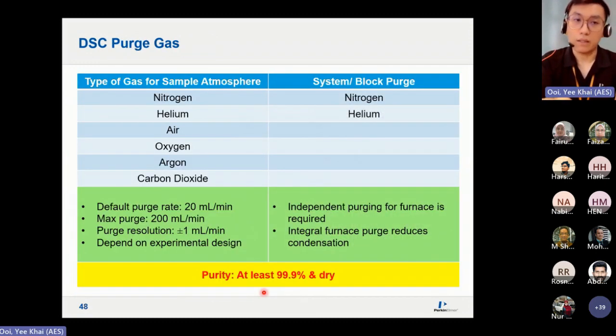Like TGA, DSC also needs a purge gas. Usually we use nitrogen. Why is it so? Although there's no decomposition, you still want your sample to be under an inert, controlled atmosphere. Hence it is run using nitrogen gas, an inert gas. Usually it's inert gases, unless you are running OIT, oxidation induction time, then oxygen is required. But usually nitrogen is sufficient regardless of your system or sample purges.